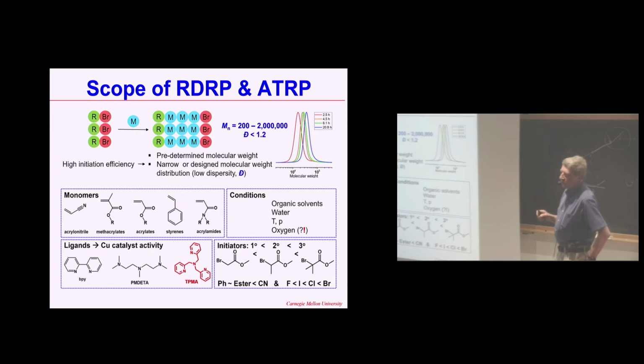So what is the scope of controlled radical polymerization? In some sense, we would like to dial whatever molecular weight or degree of polymerization we want. You can make dimers by atom transfer radical addition, and typically we go to millions of molecular weight. There are some cases of maybe tens of millions as well. We would like to have a predetermined molecular weight by the ratio of converted monomer to initiator, and also control dispersity. You can see here how narrow the molecular weight distribution is, but sometimes you would like to make it broader, meaning that you can design the molecular weight distribution.